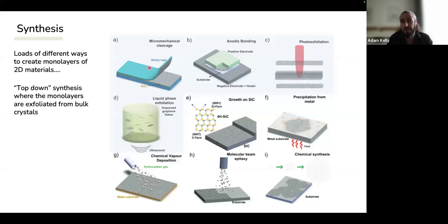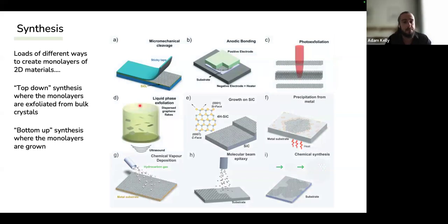The way that this was done initially in the first paper was with micromechanical cleavage using the Scotch tape method, as it's known. Other ways to do it involve using light or solution processing, which I'll speak about a bit more later. Now, the bottom-up synthesis methods as well are where monolayers are grown. So you take some substrate like silicon carbide or metal substrate, and then you deposit these elemental precursors onto it, and this allows you then to grow monolayers.